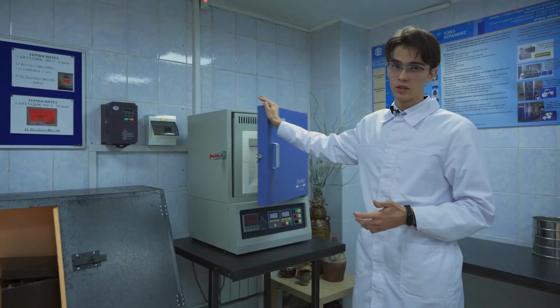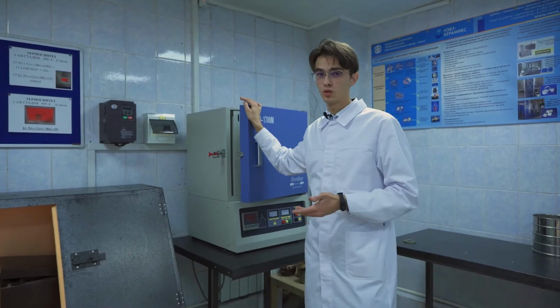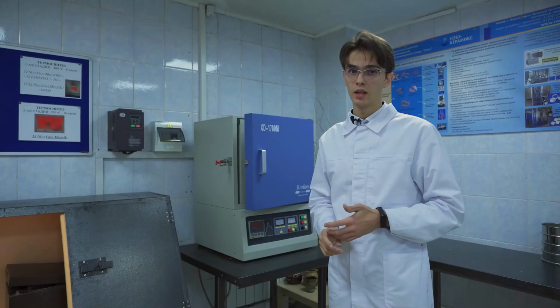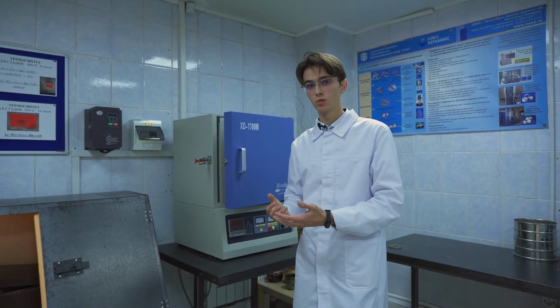We added lithium hydroxide. The idea is that the lithium starts moving fast under the high temperature in the furnace and gets into the crystalline structure of nickel, manganese and cobalt oxide. When it is inside that crystalline structure, it is already cathode material. Thanks to modern equipment, we were able to measure all the physical characteristics of the resulting cathode material in this laboratory. And that was the idea of my project. Goodbye, everyone!